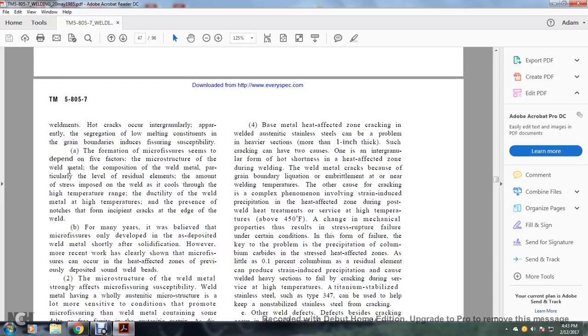Hot cracks occur with the segregation of low melting constituents at the grain boundaries, inducing fissure susceptibility. The formation of microfissures seems to depend on five factors: the microstructure of the weld metal, the composition of the weld metal, particularly the level of residual elements, the amount of stress imposed on the weld, especially in the high temperature range, the ductility of the weld metal at high temperature, and the presence of notches or insufficient fusion at the edge of the weld.